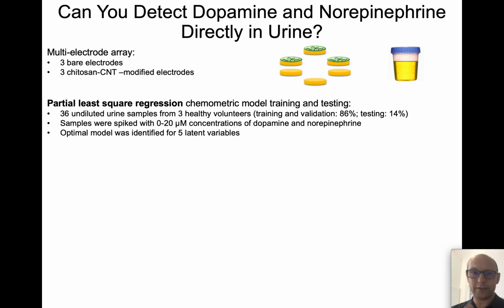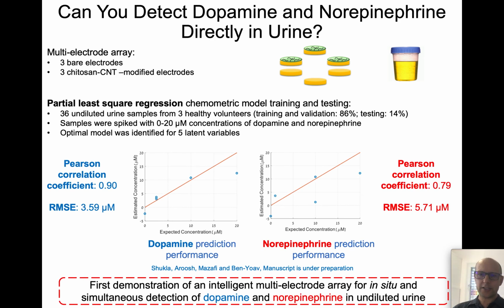Now that was done in buffer, and the question is if we can use this kind of system to measure directly in urine. So we had very enthusiastic graduate students who donated urine samples. We spiked them with dopamine and norepinephrine, did the same process, trained a partial least squares regression model, and the prediction was very good. We were able to predict dopamine with a good correlation coefficient of 0.9. Norepinephrine was a bit worse, but still good, at 0.79, and that was the first demonstration of the ability to predict both dopamine and norepinephrine directly in urine using this electronic tongue or bio-inspired approach.